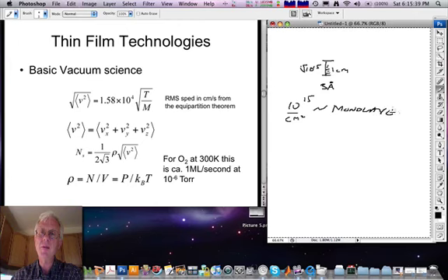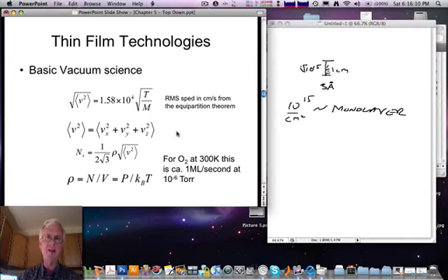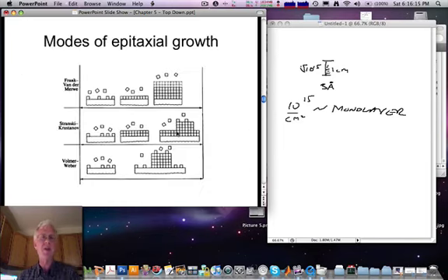So what have we learned? A monolayer of material can be deposited at a pressure of 10 to the minus 6 torr. This is quite a high vacuum. It's not the sort of vacuum that ultra-high vacuum surface scientists use, but it's a good kind of vacuum to get with an oil pump and a bell jar. And you can see that even in a vacuum like this, one monolayer per second is being deposited on the surface. So in order to get thin films cleanly deposited on surfaces, one has to work at very much higher vacuums and remove the films that will have been on the sample surface when you put it into the vacuum chamber in the first place.